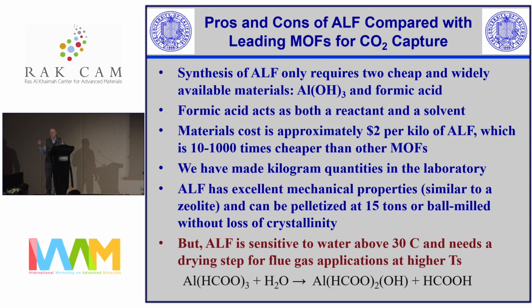So when we calculate the Young's modulus, bulk modulus, shear modulus, and so on, they're similar to a zeolite rather than a MOF. And MOFs are notoriously fragile, especially the ones with large cavities. Whereas with this, we can make pellets of 15 tons without any problem, and we can ball mill it without losing crystallinity. We can actually make nanoparticles of it just by ball milling it. So it has a lot of advantages.